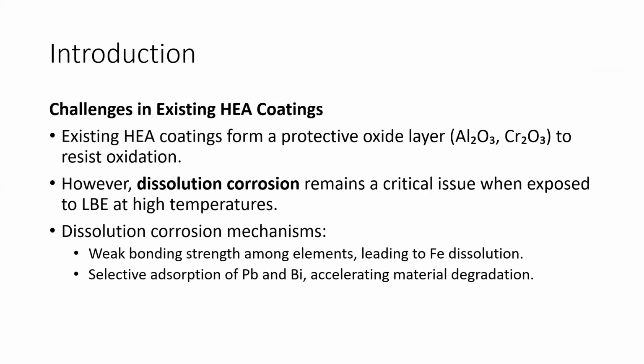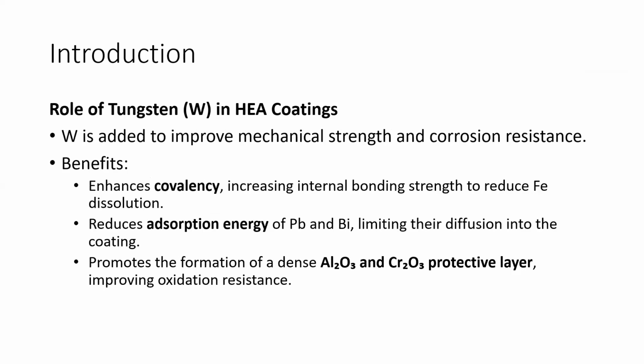So, the challenge in existing HEA coatings: we know that existing HEA coatings form a protective oxide layer like aluminum oxide and chromium oxide to resist oxidation. However, dissolution corrosion remains a critical issue when exposed to high temperature LBE. Dissolution corrosion mechanism: 1. Weak bonding strength among elements leading to iron dissolution. 2. Selective adsorption of Pb and Bi, accelerating material degradation.